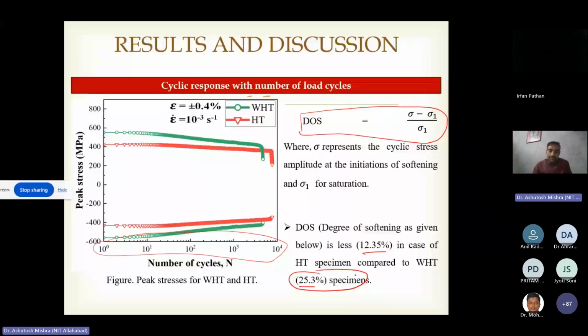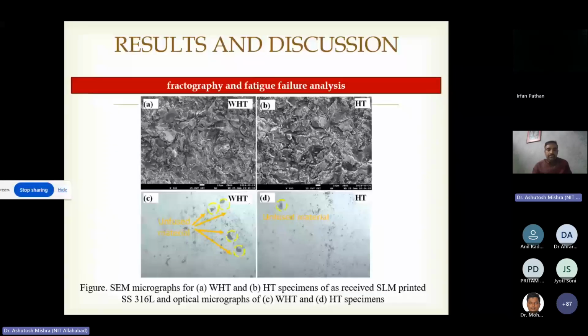And the relation of degree of softening with strength is already established, and the same we have observed for this particular test also. Then we have carried out the fractography and fatigue failure analysis, wherein we see that there is more unfused material in WHT. However, after heat treatment, unfused material is less, and this again concurs with the existing knowledge that heat treatment actually reduces the unfused material.